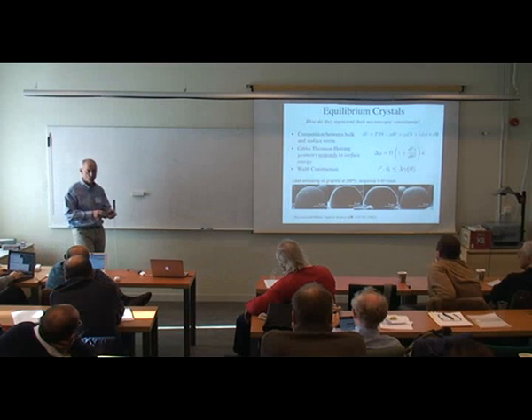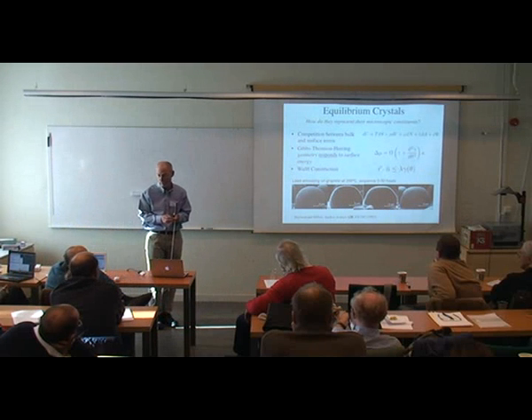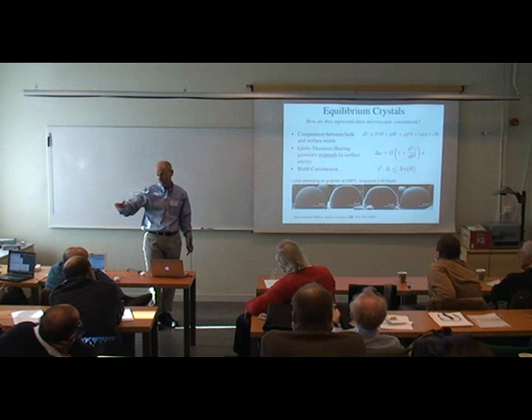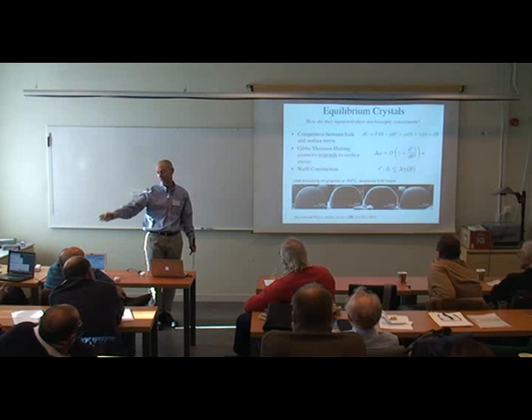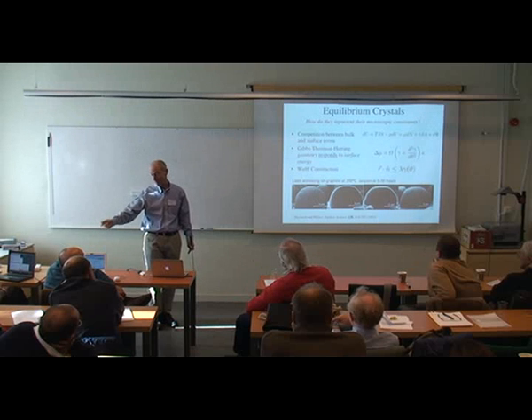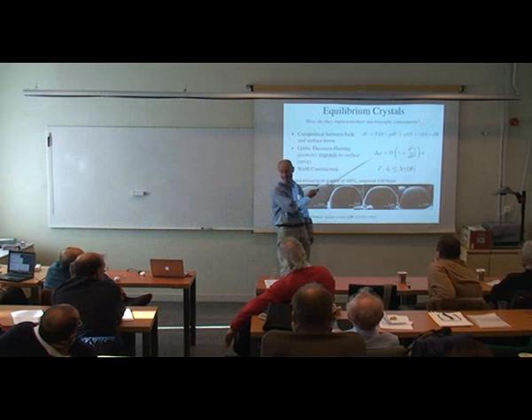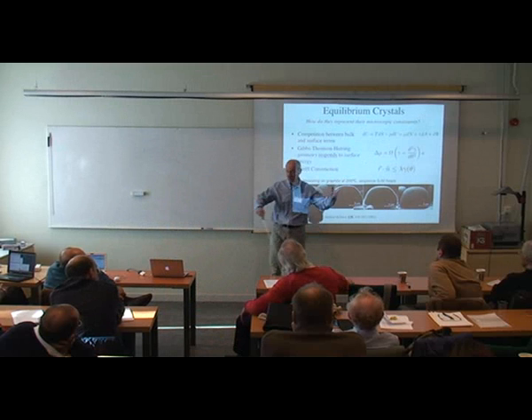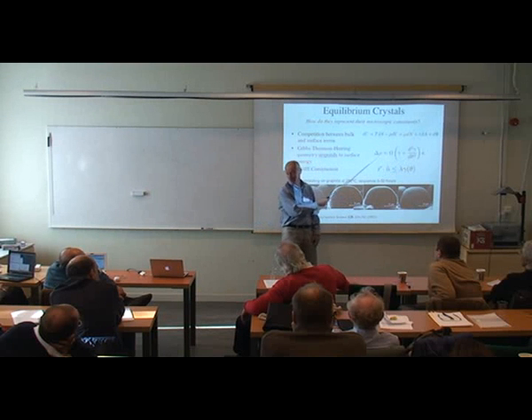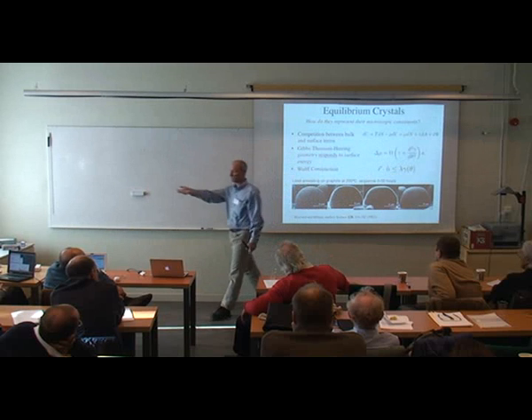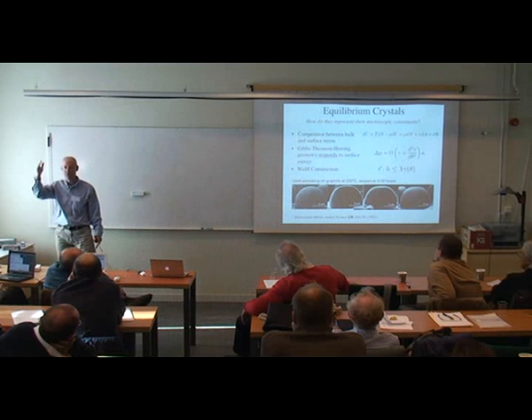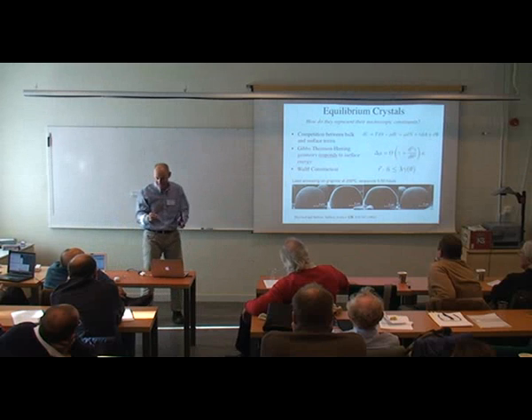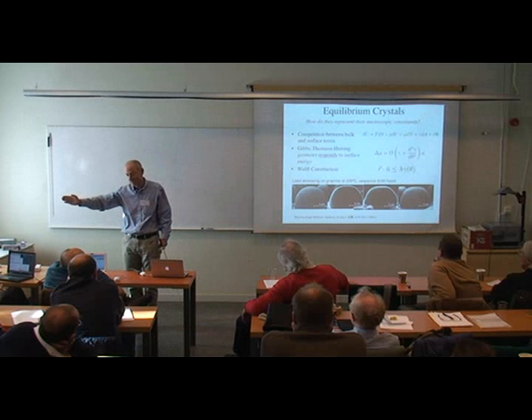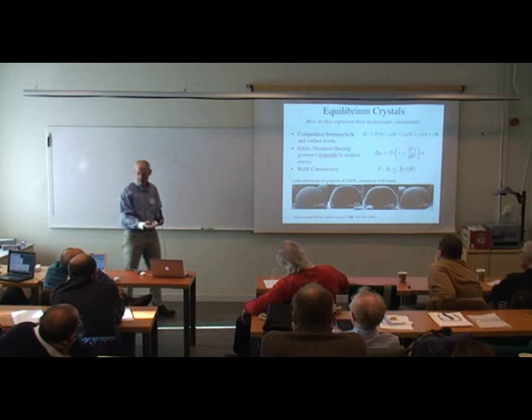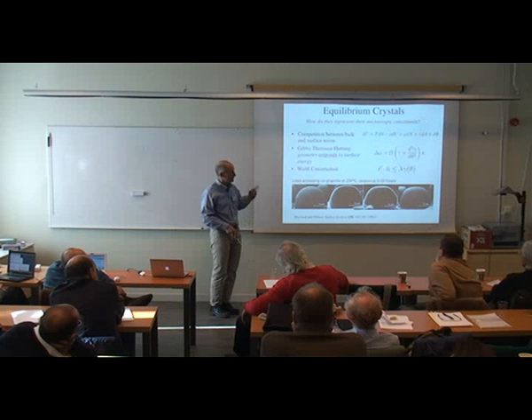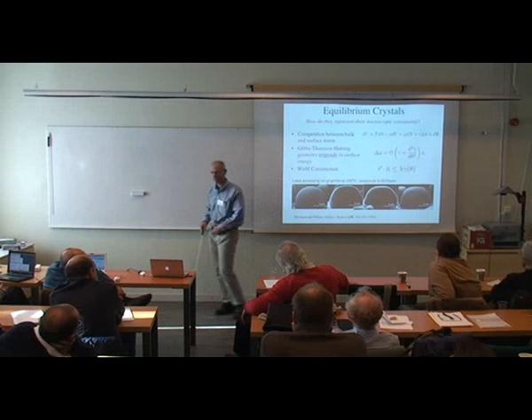It's general. You're familiar with the fact that small objects have a lower melting temperature, right? So a metastable equilibrium of a small solid in contact with its melt is shifted from the bulk phase diagram by delta mu. In bulk coexistence, the size is arbitrarily large, and so delta mu goes to 0. The invariant as you move around the surface is that delta mu has to be fixed. So the geometry, the product of the surface stiffness and the curvature, is fixed: as the stiffness increases, the curvature must decrease. That gives you the underlying structure, but that, if you will, is a boundary condition that has to be satisfied on the surface.